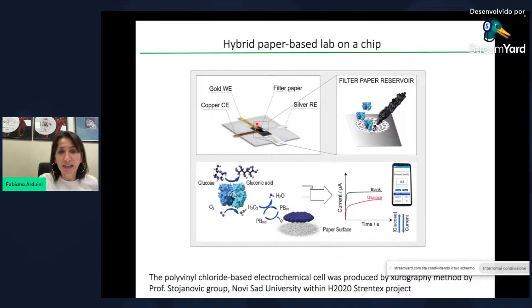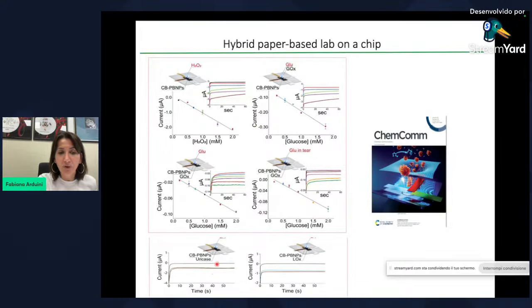And we demonstrate that by changing the strip, it's possible to detect different target analytes. Indeed, for example, by adding a strip preloaded with uricase, you detect uric acid. If you preload this strip with lactate oxidase, we are able to detect lactate. This is published in Chemical Communications.